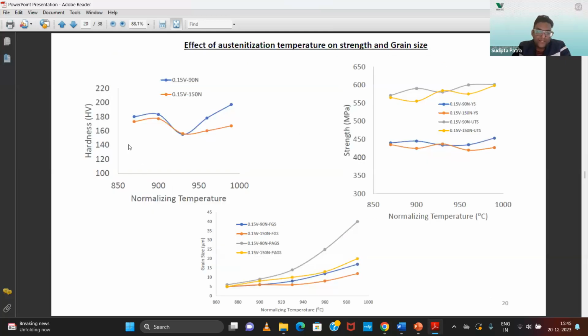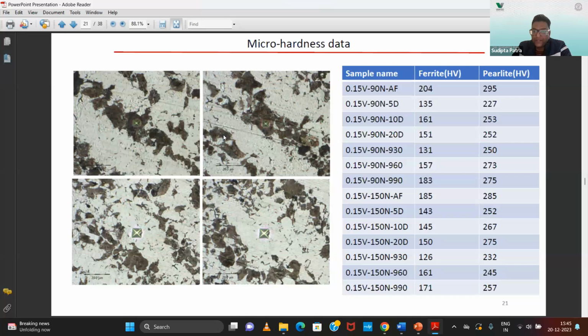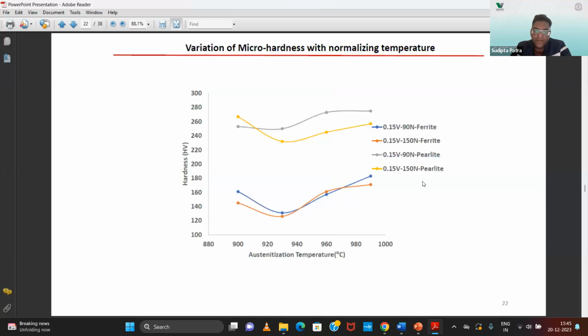So the precipitation strengthening effect will show good hardness also here with the normalizing temperature. And we can see the micro hardness in the ferrite region. You can see that in the as forged condition we could see 200 Vickers hardness in the ferrite itself, and at 990 degrees centigrade we could again get 185 hardness.